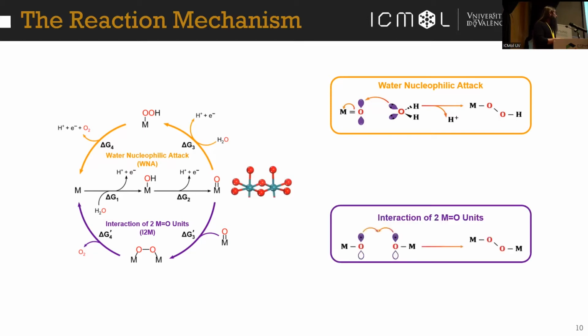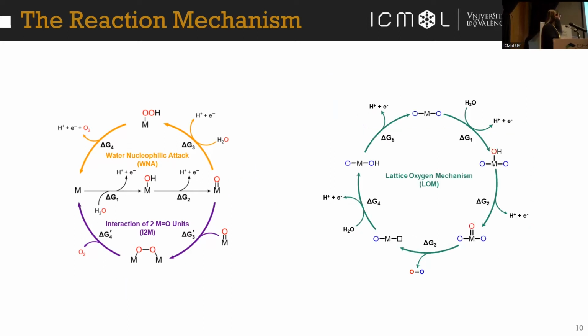These 2 oxygens will interact to form a peroxo unit, and then oxygen evolves from this species, and we recover the catalyst again. And the third reaction mechanism is known as the lattice oxygen mechanism.